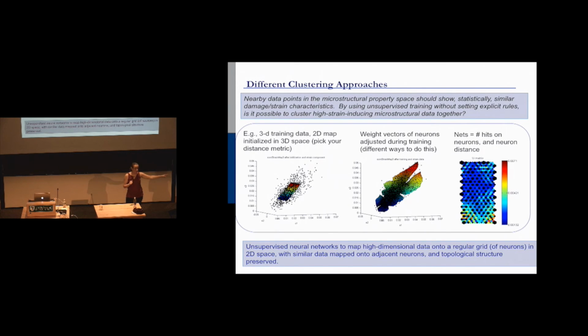And you do this for thousands and thousands of damage maps until you get a good match that occurs over and over and over again. The best match that you can find. And that starts to tell you which microstructural variables are important. The way that you cluster the microstructural data, the way that a self-organized map works: take the data points, throw them in 100-dimensional space, take a neural net, throw it on top, let the data points pull the neural net, so that you have the best cluster possible.